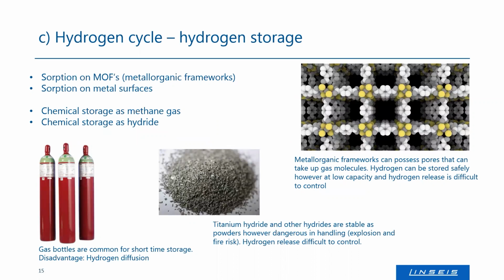Having a closer look at the sorption, the typical hydrogen sorption takes place at metal-organic frameworks, which is a structure consisting of a metal grid with an organic surface, and the organic ligand or the organic molecules at the surface usually are responsible for forming pores within which hydrogen can be located. And these MOFs or even zeolite structures, which is a ceramic structure also with little micro nanopores, they can all adsorb hydrogen by pressure and release it if the pressure is reduced, or they can adsorb hydrogen by temperature. If there's hydrogen present and you lower the temperature, they will adsorb it. If you increase the temperature, the hydrogen will be released again. So that's what's going on regarding sorption.